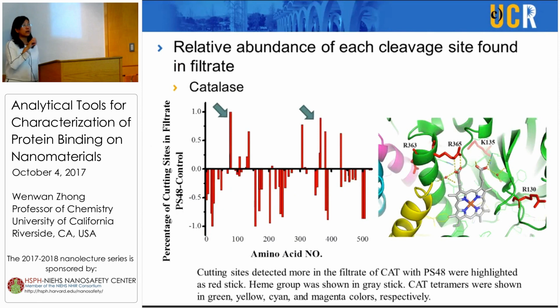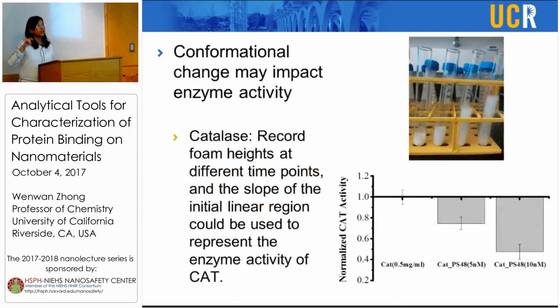So then when we move on to study the activity change, indeed we see catalase activity is being significantly reduced after it binds to polystyrene particle with the diameter around 48. So the top picture shows the foam test, showing the oxygen generation catalyzed by catalase, and we use the foam generation to illustrate the activity of the enzyme and show the enzyme activity reduction after binding to the particle, which we believe is because the binding site is very close to the activity center.